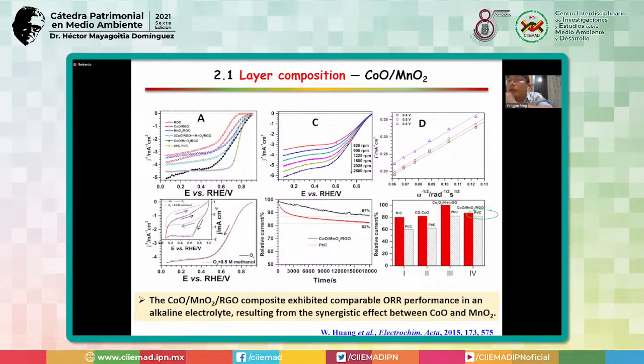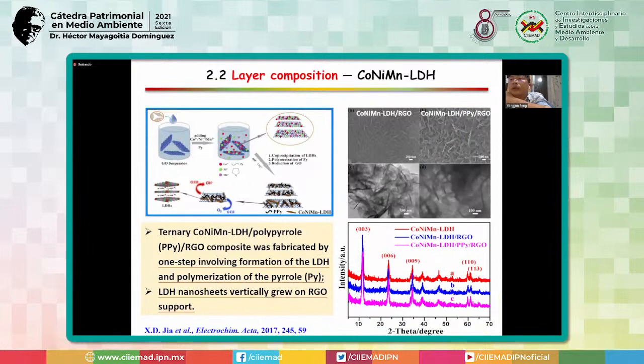So we can show different electrochemistry because on both sides there is very nice, higher dispersion. That one is different from what you synthesize by other chemical synthesis. So the LDH is a precursor. Or in another one we change to nickel, cobalt, manganese for the host sheet. That means the ternary cobalt nickel manganese LDH, also with the polymer PPY together, fabricated in one step involving formation of the LDH and then polymerization of PY. Also the LDH sheets grow vertically on RGO for support. So we can get very nice dispersion and very nice conductivity.